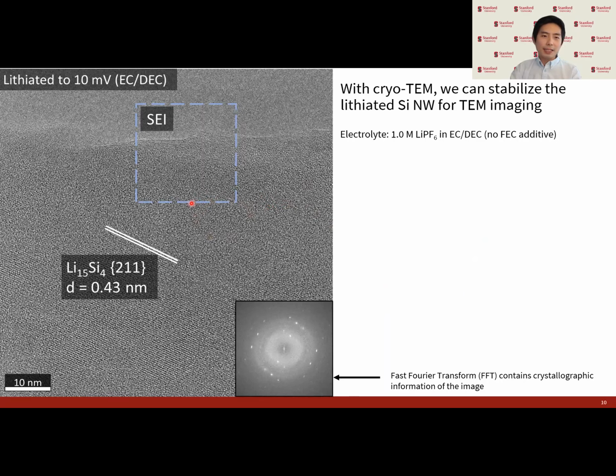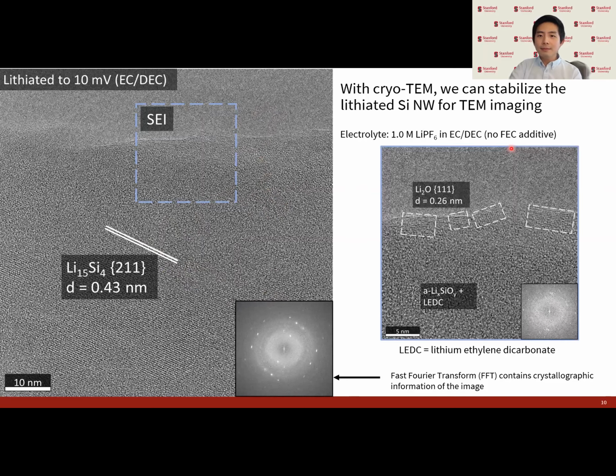So this probably looks like mostly just gray, but down here what we can see is that we have a crystalline lithium silicide core. That's this Li15Si4 phase, which is the most lithium-rich phase of the lithium-silicon phase diagram. And out here is vacuum. But in between here is the SEI, which is what we're interested in. And this is all in the electrolyte without any FEC additive. If we then zoom in on the SEI, we can see that there are crystalline lithium oxide domains along with a lot of amorphous components.